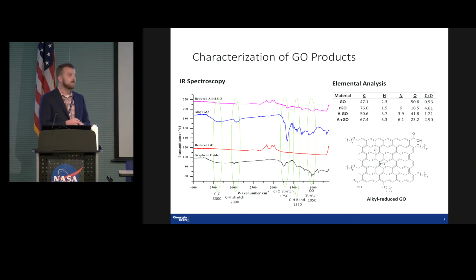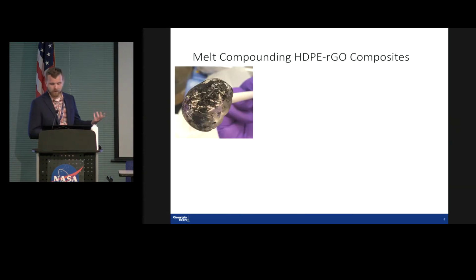Another thing we can look at is the elemental analysis. What I want to draw your attention to is this carbon to oxygen ratio column here. The higher the carbon to oxygen ratio, generally speaking, the higher quality of reduced graphene you have. So reduced graphene oxide has the most carbon relative to the least amount of oxygen. And then we see that upon functionalization with the alkylation agent, this number goes down a little bit, from 6.61 to 2.9. That's also indicative that we have these ether linkages there that have this oxygen atom in them. And so this is what we want to see. It's a good thing. That means that our chemistry has worked.